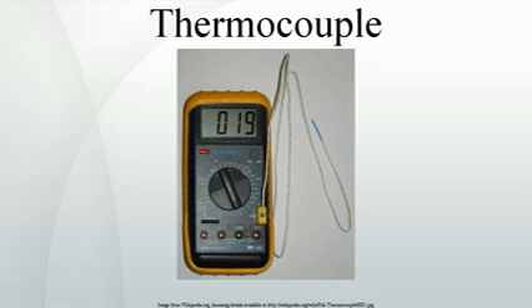As thermocouples age in a process their conductors can lose homogeneity due to chemical and metallurgical changes caused by extreme or prolonged exposure to high temperatures. If the inhomogeneous section of the thermocouple circuit is exposed to a temperature gradient, the measured voltage will differ, resulting in error. For this reason, aged thermocouples cannot be taken out of their installed location and recalibrated in a bath or test furnace to determine error. This also explains why error can sometimes be observed when an aged thermocouple is pulled partly out of a furnace, as the sensor is pulled back.